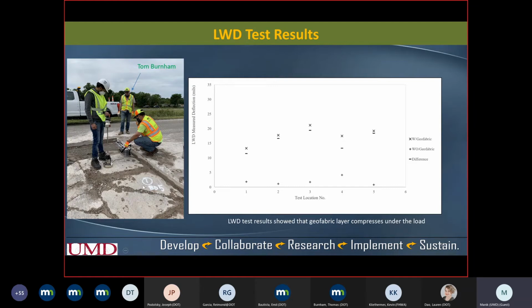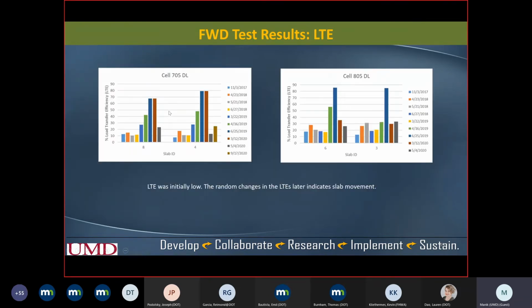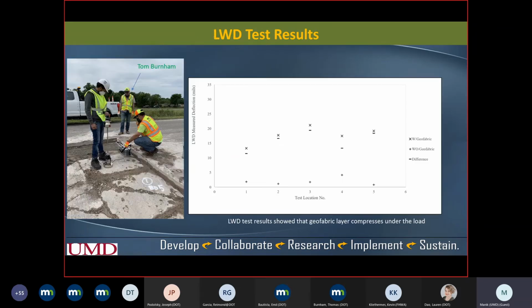Now we did a small test when some slabs of cells 805 and 705 were replaced. Here's Tom. Actually, we were doing the test under his supervision. This is a lightweight deflectometer, and we did the test right on the concrete and also on the geofabric. But you see, when we did the test on the geofabric, it shows really high deflections, and when we did not have the geofabric layer, the deflection is far less. So the load transfer efficiency results and high deflections under the FWD load make sense, because the geofabric was probably absorbing some of the load, creating high deflections.